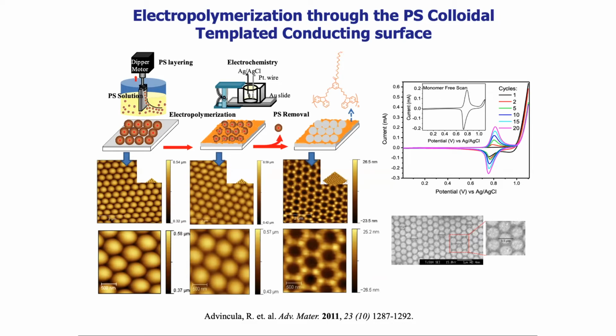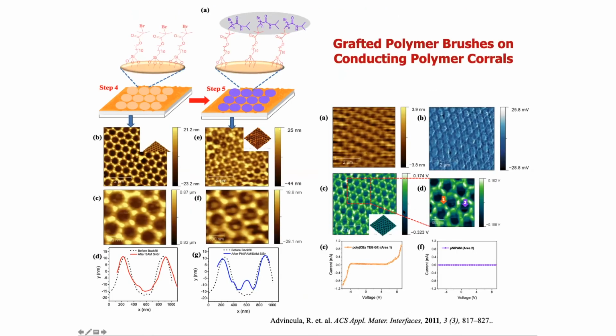Here, we demonstrated the deposition of a conducting polycarbazole through these polystyrene patterns, resulting in an array of this conducting polymer, and again, monitoring the deposition by CV, or cyclic voltammetry. Now, what we have in the middle are basically blank spaces of the substrate. This exposed area of the substrate can be grafted with an ATRP initiator, and then you can grow a polymer brush, in this case, polyNIPAM, so that you get a polymer brush within those conducting patterns as shown here.